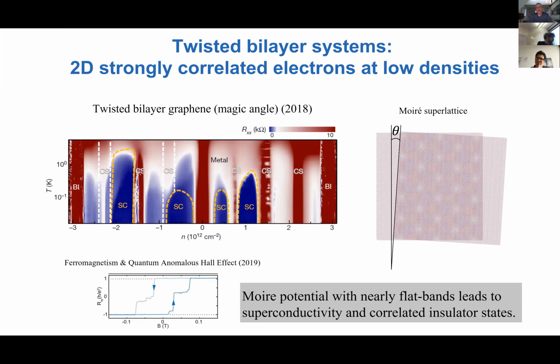Okay, so regarding the possibilities, over the last 2 years, there has been an explosive growth of research on twisted bilayer systems, and particularly twisted bilayer graphene. What makes this system interesting is that it has a very rich phase diagram. As you dope the system, you can go from relatively simple insulating states, I guess this is the band insulator that you obtain when you heavily electron dope or heavily hole dope.